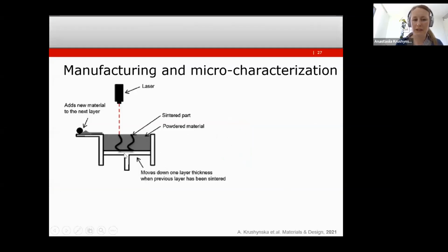Yeah, so what I mean is that the lowest part of the structure here will have higher material density as compared to the top part of the structure, because the taller or the larger the structure along the printing direction, the lower is the density, and the difference can be crucial, especially if we want to have highly loaded structures.